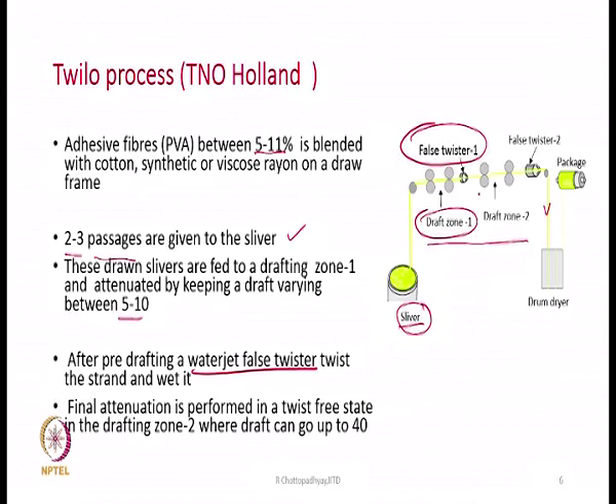Now comes the second drafting zone. In the second drafting zone, the draft can go up to 40. So, there is a range in which we can keep the draft here, because now after the second drafting zone, we have to reach the stage of the yarn or the dimension of the yarn. So, we can keep a draft of 30 or 35, 32, whatever we require, accordingly we can keep the draft, and we bring the bundle of fibers to the dimensions of the yarn, whatever yarn count we want to produce.